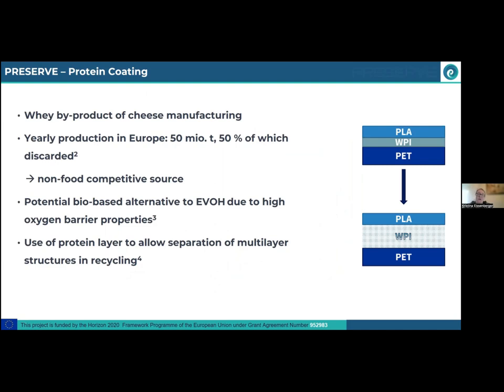And you can use this protein layer to allow for separation. As you can see here, these are theoretical, very artificial multi-layers of PLA, whey protein coating, and PET. During delamination, this protein layer is dissolved and degraded, and then the two polymer substrate films can be separated again and can be fed into their respective material cycles.